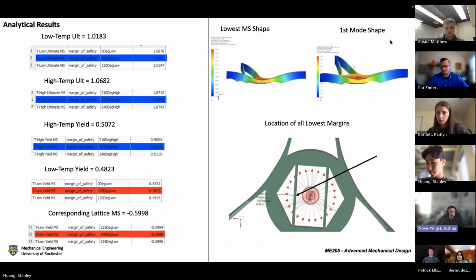Okay, so this is the ultimate and yield margin of safety. The lowest margin of safety was low temp yield, which is about 0.48. If you include the lattice in there, it drops down to about -0.6. So what that tells us is, at least yield-wise, the overall model will not yield, but the lattice probably will. So we thought that could present some potential stiffness issues.